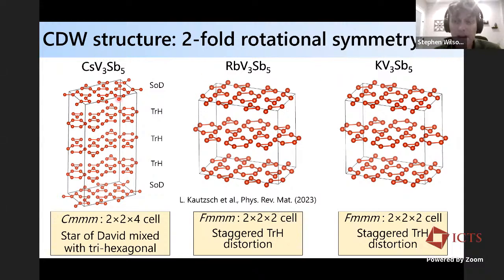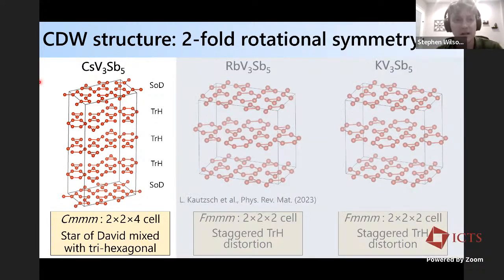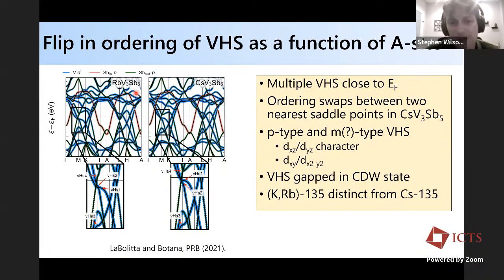But for the cesium system, there are actually charge superlattice peaks at a different wave vector as well. They're at the 2 by 2 by 4 enlargement of the unit cell. If you look at the average structure, meaning assuming a single phase across the whole sample, then you get a pattern of staggered and mixed trihexagonal layers, as well as the so-called Star of David, which is the inverse version of that. The trihexagonal is sometimes called the inverse Star of David as well. So you have a much more complicated structure, and that's what I'm going to be focusing on in this talk, because the cesium system is somewhat unique from the other two in subtle ways.